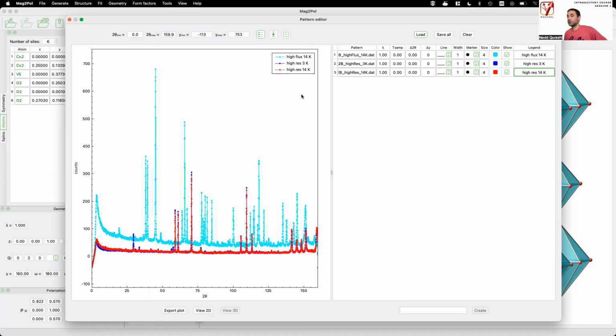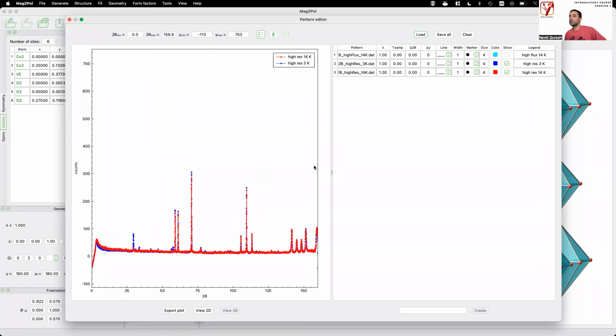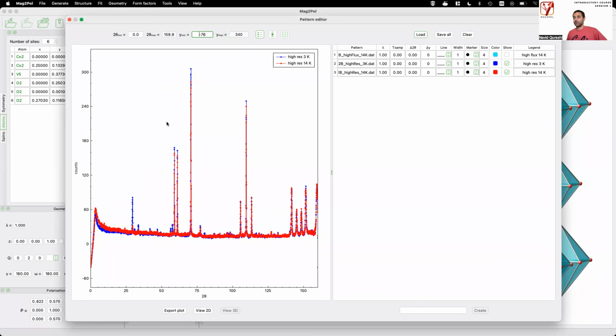What I wanted to show you here, so these 2 patterns will be the ones which we will refine in a few minutes. And what I wanted to show you is if you look at those 2 patterns, and I can right click here to reset the boundaries, so it will fit the data better into the window. So it's the same compound at 2 different temperatures, and one is above a magnetic transition and the other is below. So this additional intensity shown in blue comes from magnetic scattering,